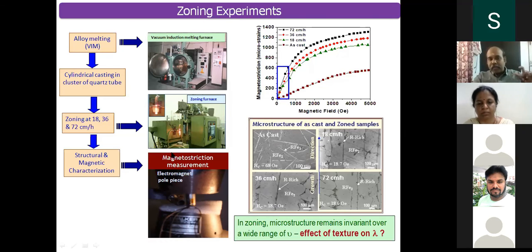We pulled at around 18, 36 and 72 centimeters per hour, and we also characterized for magnetostriction. The first and foremost thing we see in any material is the microstructure. When we see the as-cast microstructure, I mean the material has melted, I could see the matrix phase, that is the phase which I wanted, particularly the RFE2 phase. In addition to this, I am also able to see the RFE3 phase. That means the peritectic reaction is not complete here.